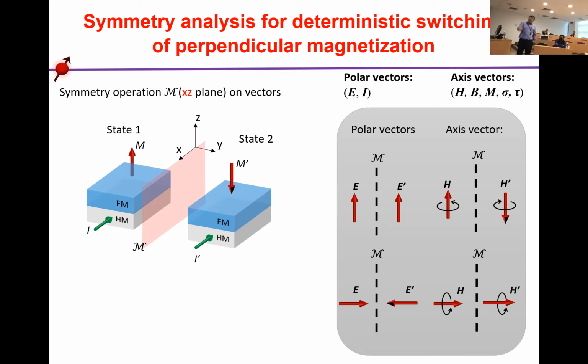When you apply the mirror symmetry, the electric current does not change. Only the magnetization has reversed direction. So this indicates that when you apply this direction of current, the polarization up and down is energetically equivalent. So therefore, you cannot use this electric current to switch the magnetization.